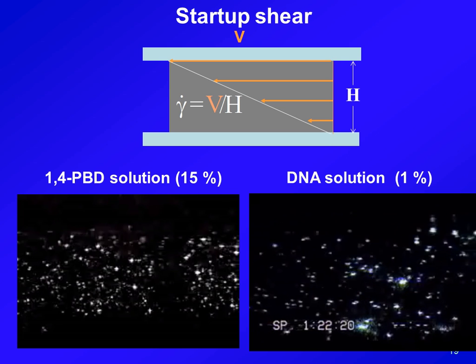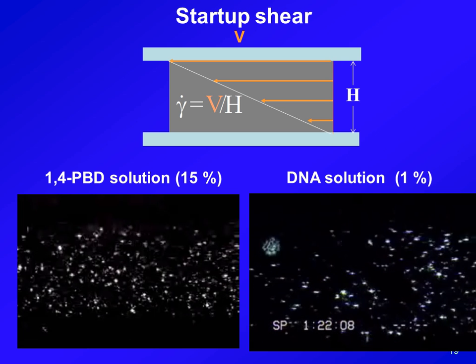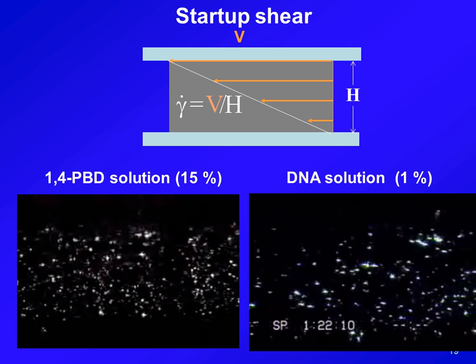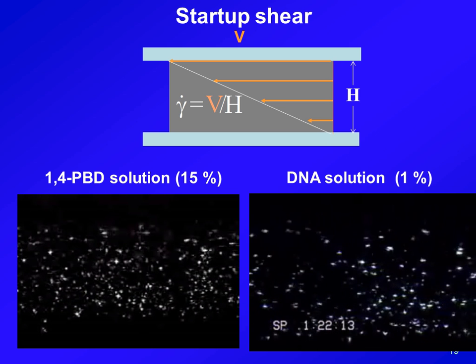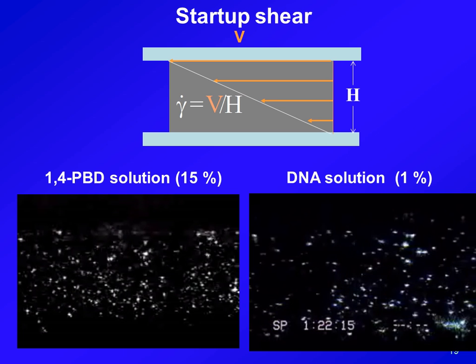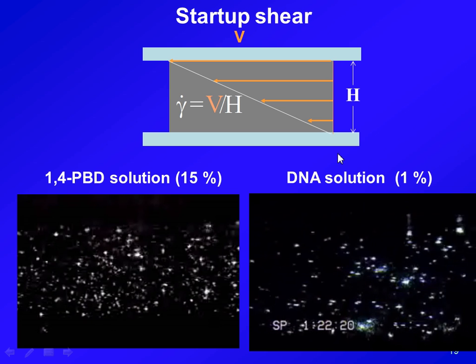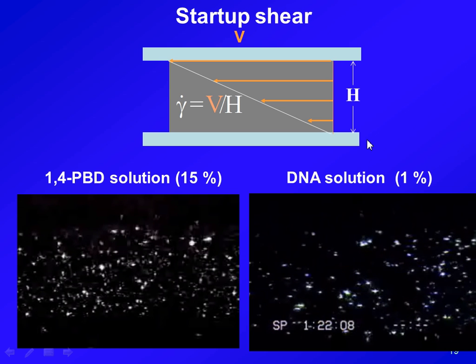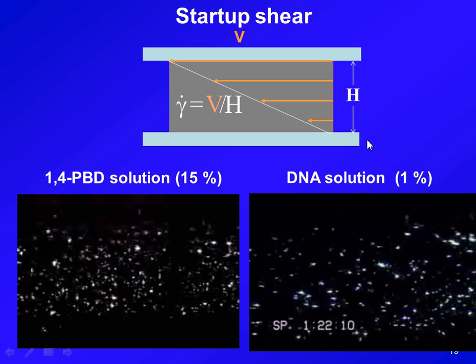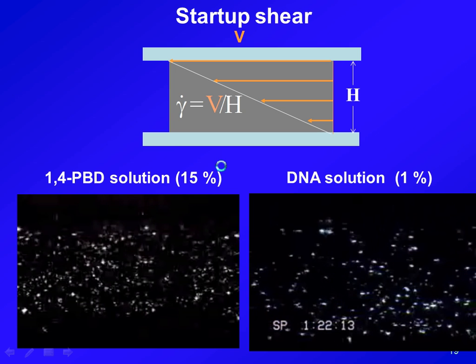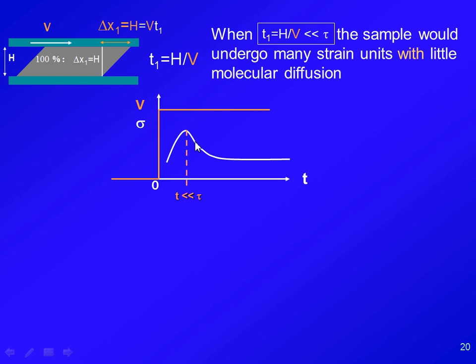For those who have sharp eyes, you see the beginning part is homogeneous. And then the sample broke apart. So that homogeneous deformation is really a moment where the force is still monotonically growing, and the point of breaking is beyond that homogeneous rise. So the breaking occurs after the maximum has appeared in your stress signal, the force measurement.